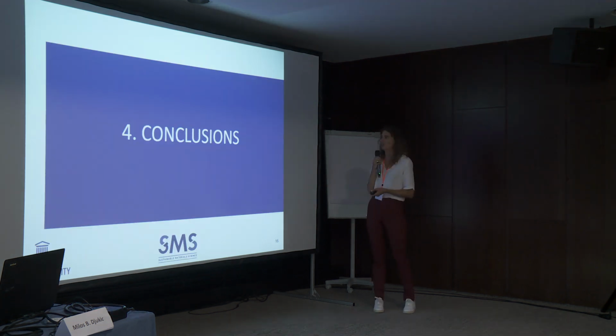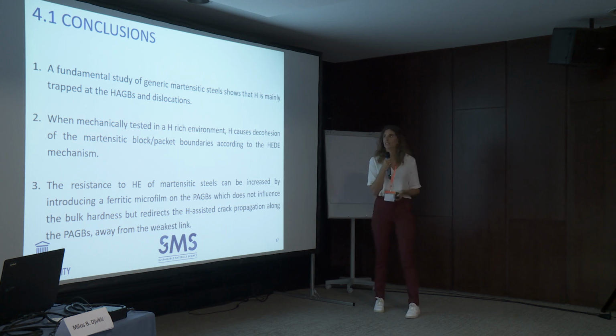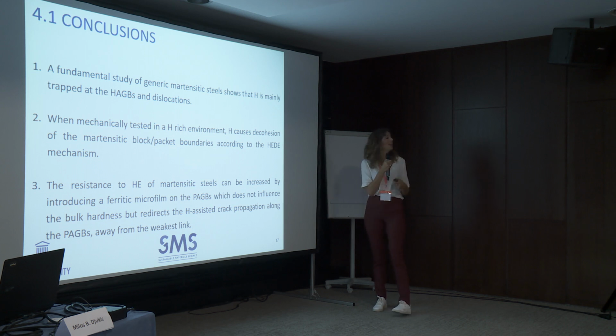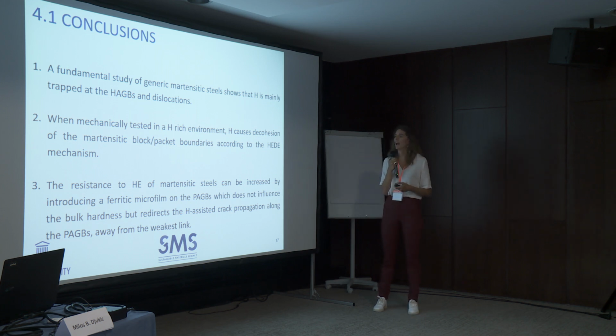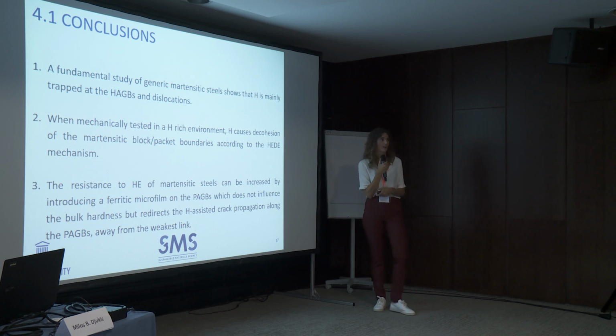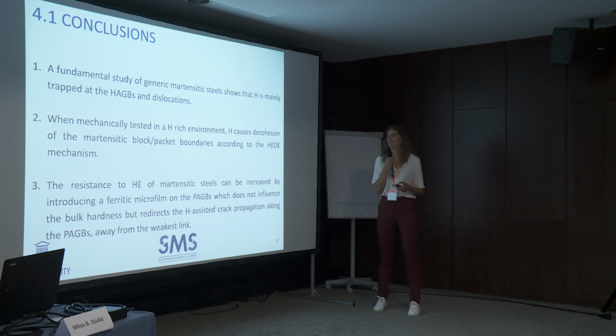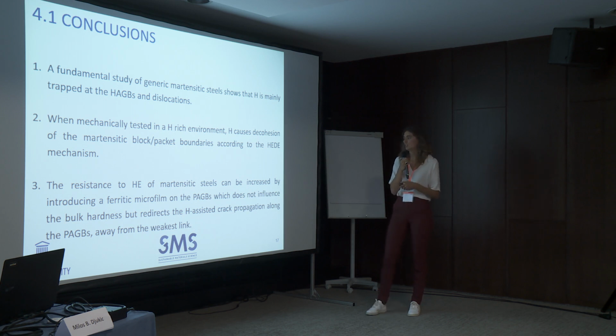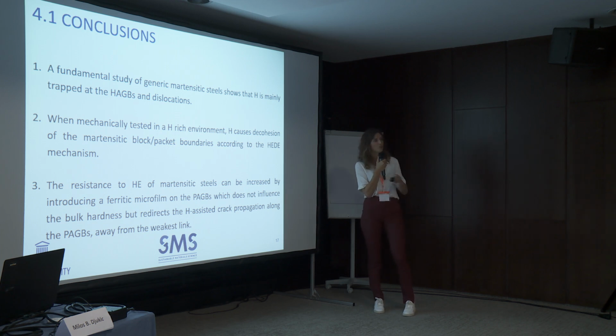So I can go over the conclusions. I did a fundamental study of the hydrogen trapping behavior in generic iron carbon steels, and I saw that hydrogen is mainly trapped at the grain boundaries and the dislocations. When these types of steels are mechanically tested in a hydrogen-rich environment, hydrogen will cause a transition to a cleavage type of fracture, which can be linked to the HEDE mechanism, and the resistance of these steels can be increased by introducing a ferritic microfilm on the parent austenite grain boundaries, which does not influence the bulk hardness, but it redirects the hydrogen-assisted crack propagation along the parent austenite grain boundaries and away from the weakest link, which are the packet